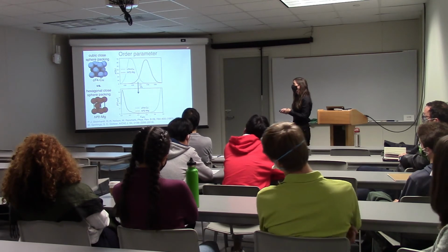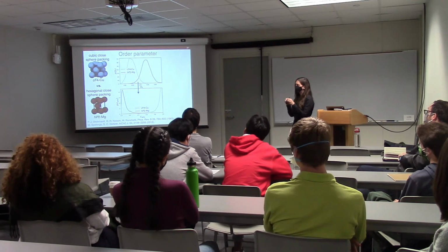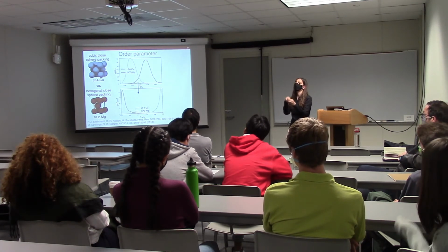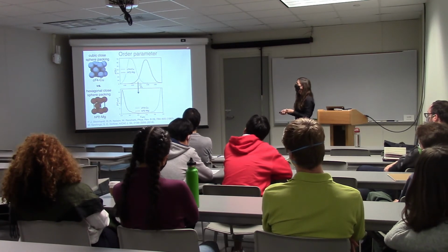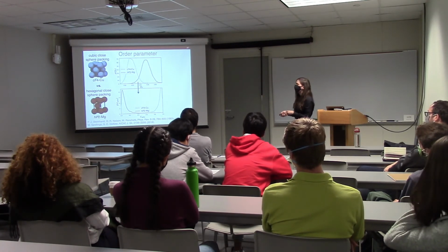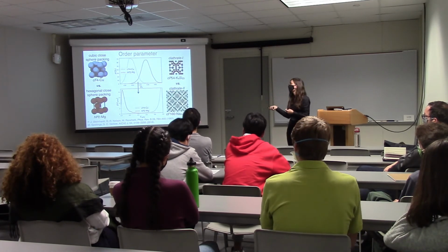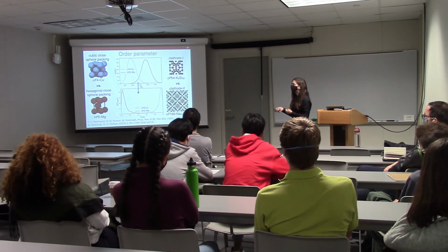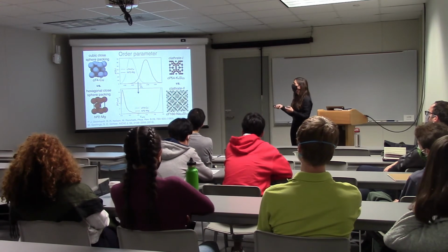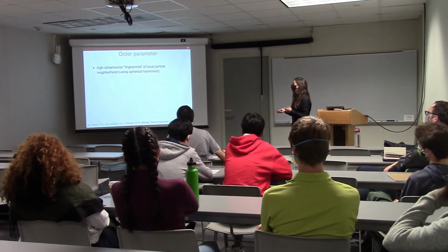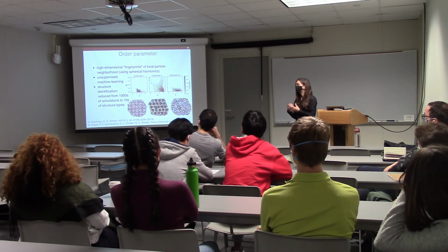So the order parameter that we're using is way more high-dimensional, and it takes the local environment apart essentially into where do the 4 nearest neighbors sit, where do the 5 nearest neighbors sit, and so on. And you're able to suddenly tell those two structures apart way, way better, up to the point that you can tell apart different clathrate-like structures that locally all look like little tetrahedra and have huge unit cells. We're still able to distinguish them if we use a high-dimensional order parameter and machine learning to evaluate it, because otherwise we can't make sense of this data.